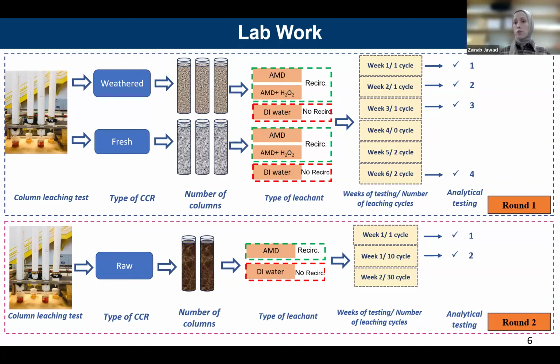We did 2 rounds of column leaching testing. In the first round, we used the weathered and the fresh refuse. We filled 6 columns, 3 for each type, and then we used 3 leaching solutions. The first one was the acid mine drainage. The second one was acid mine drainage with added hydrogen peroxide as an additional oxidizer. And the third one was DI water.